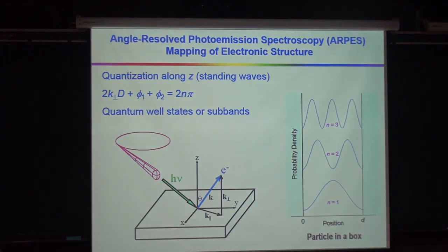Okay, so getting to science, as I mentioned, we use ARPES to measure the electronic structure. This is how we do it. So here's a storage ring. Light comes out and goes onto a sample, and we excite electrons that come out. The energy of the photons is typically in the range from a few electron volts to a few tens of electron volts, and the energy is high enough to overcome the work function, so the electrons come out. We just measure the angular distribution and the energy distribution, from which we back out the electronic structure of the system in its original ground state. By energy conservation and momentum conservation, we can back out where it comes from.